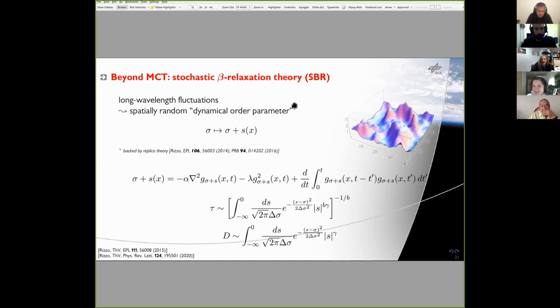So this is my one slide summary of stochastic beta relaxation. You've seen those plots, actually. You've seen this equation. And I just wanted to remind you of the two asymptotic predictions that Tommaso and I backed out of this equation, which relate to the structural relaxation time and the diffusion coefficient. And there's, if you like, a little bit of an additional ad hoc assumption where we say the structural relaxation time should be dominated by the average relaxation times of the system.